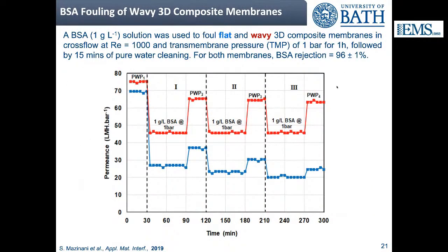And we then switch from oil and water to BSA, because that is a very classical, let's say, foulant that represents biological fouling. So here is a similar experiment. In blue, you have the flat membranes. In red, you have the wavy ones. And you have the same behavior: an initial decrease in permeance due to fouling when you switch to BSA. We keep the BSA fouling ongoing, in this case, for 60 minutes.